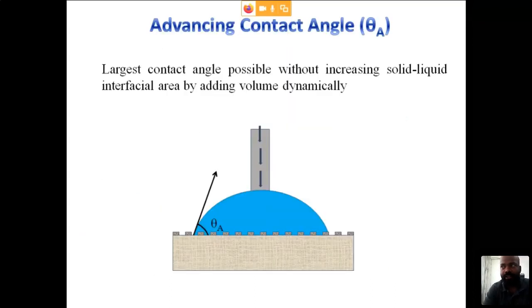Whenever you are measuring contact angle or wettability of any surface, it cannot be measured only with the contact angle. Contact angle sometimes is not the complete result. So we have to mention something called advancing contact angle and receding contact angle. Whenever you are measuring the advancing contact angle, you have to increase the droplet amount during the measurement. I hope whoever is involved in this kind of research will know well about this advancing and receding contact angle.